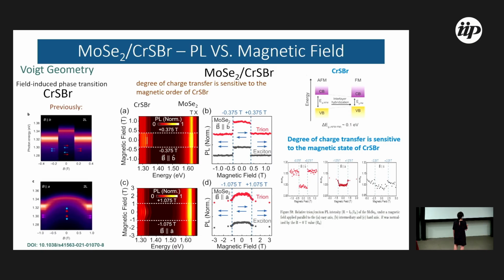This is evident because if you plot the relative intensity of exciton and trions, if the trion intensity is stronger, it means more doped. You can see that the relative intensity of trion and exciton changes with the phase transition. This is clearer when we align the field with the z-axis, but in all cases it happens. It's more complicated to see here because we have valley effects that I will explain in the next slide. So we can use the PL intensity of exciton and trions as a sensor of the phase transition.